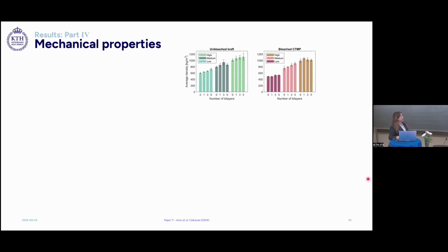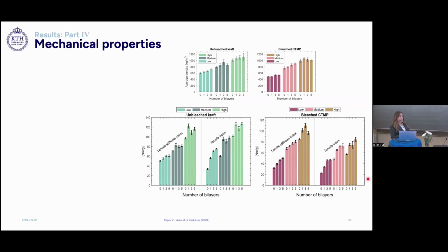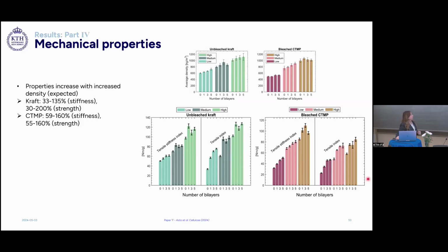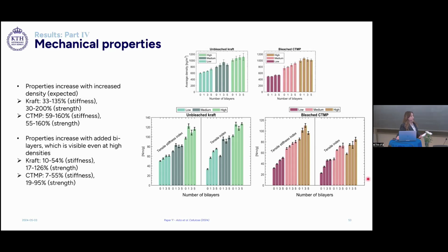Next, we studied the mechanical properties of these LBL treated papers, and we can see from the specific stiffness and strength properties of the papers that the properties increase with increased density for both materials. And also, the properties increase with the added bilayers, which is also seen at high densities.